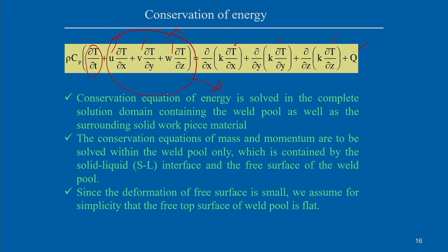The conservation of energy equation is solved over the complete solution domain, including both the weld pool and surrounding solid workpiece material. Within the weld pool there are velocity components u, v, w for energy transport; in the solid domain there are no velocity components, so convective terms do not apply. The conservation of mass and momentum equations are solved only within the weld pool, which is defined between the solid-liquid interface and the free surface of the weld pool.